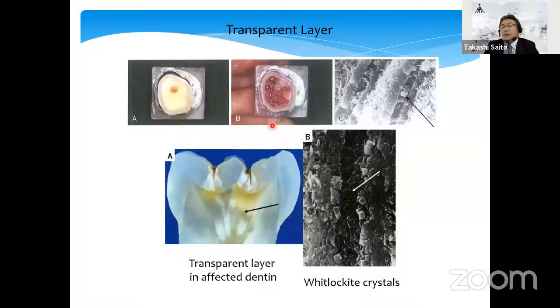The red dye solution was pressure-injected from the root pulp chamber. The dye solution cannot penetrate the caries region to the upper side. The whitlockite, a precursor of hydroxyapatite crystal, deposits in the dentinal tubules. It functions as a defense, so we need to be careful to preserve this protective layer.